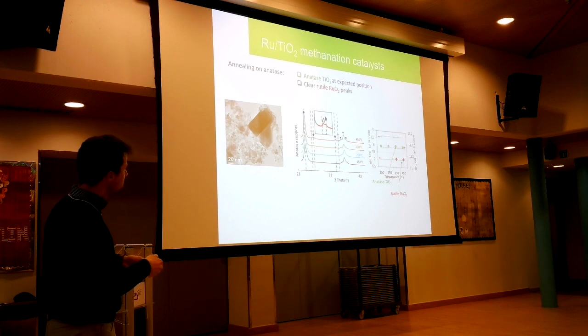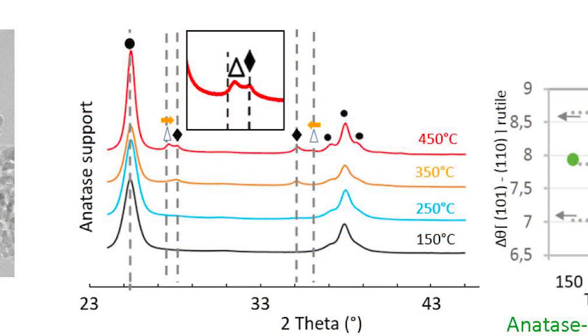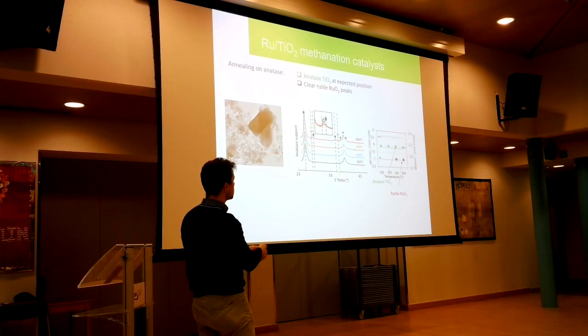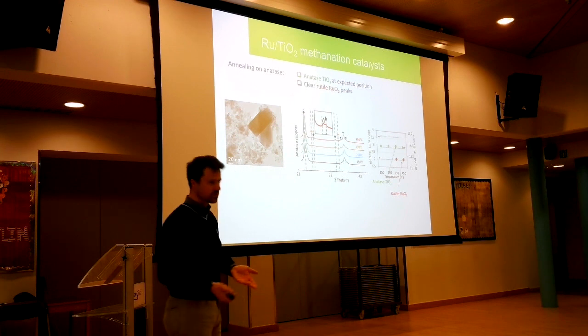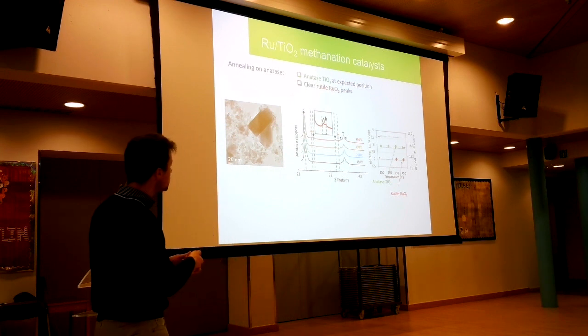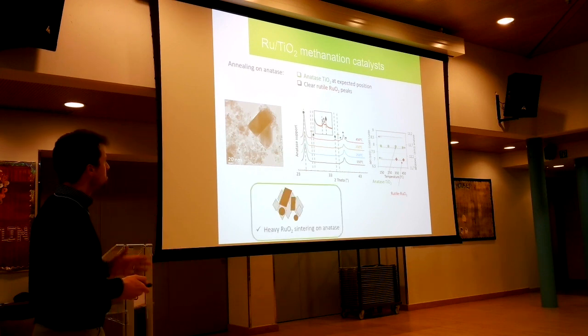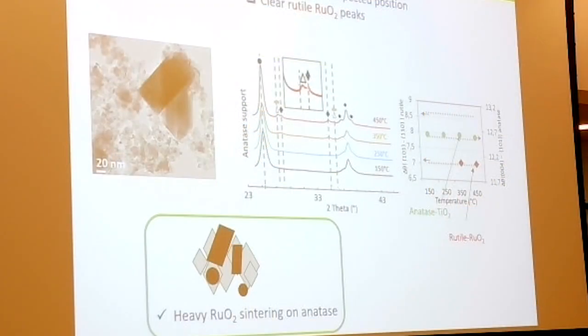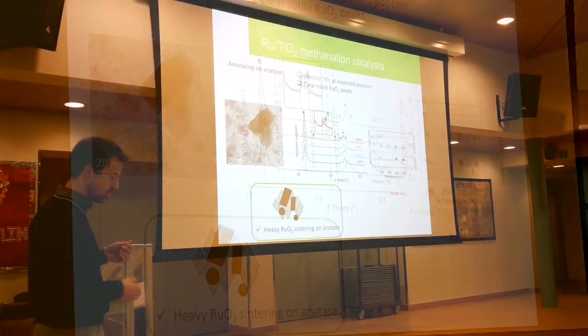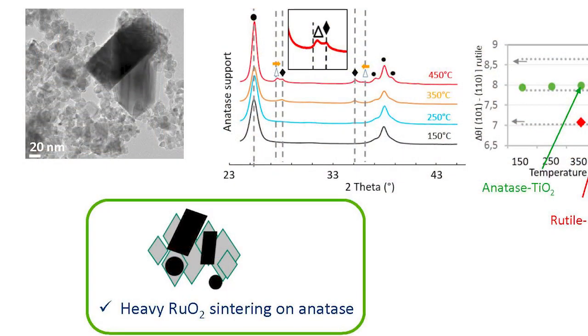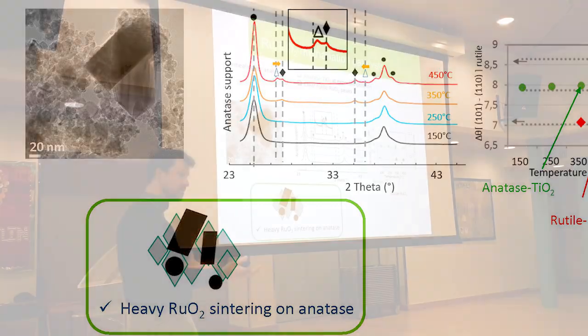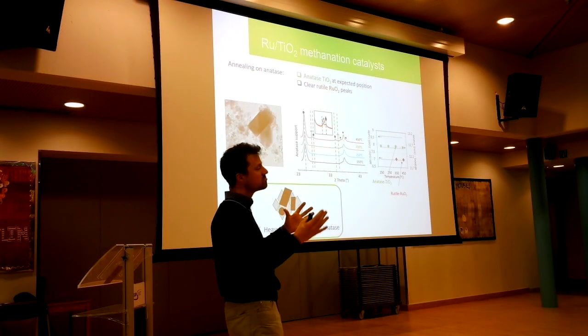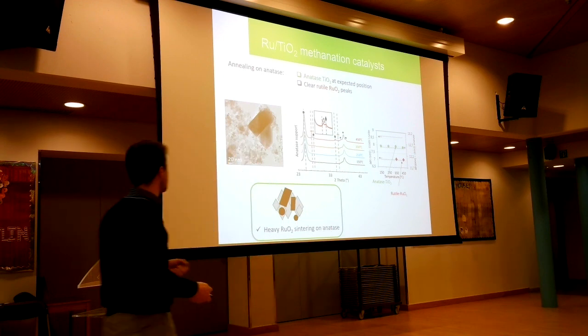At low calcination temperature, we don't see ruthenium or ruthenia, but when we increase the calcination temperature, we start to see those diamonds here, rutile ruthenia. So this is the classical phase in which ruthenium dioxide will crystallize. So it landed exactly where it was expected, so no big surprise there. Okay, but the peaks there were not tiny, and they were a good indication of the fact that you have a big sintering, so agglomeration of the ruthenium oxide, formation of relatively big crystals. I remind you, big crystals, not so good for catalysis because you lose some active surface.